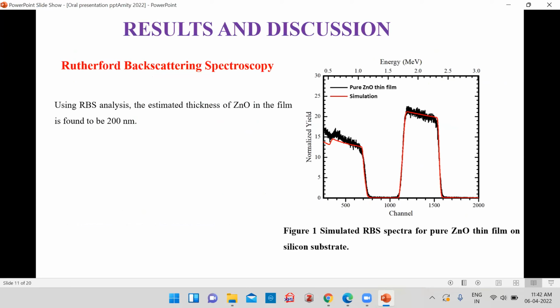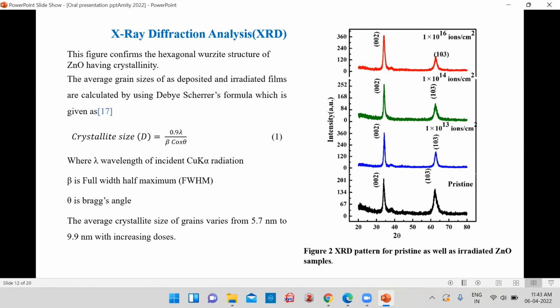This is my XRD pattern of pure ZnO as well as irradiated thin films, which we have done for structural analysis. Two major planes, 002 and 103, are found, and we can see that after irradiation the planes remain stable. This gives stability in the structure, and the 002 plane gives the hexagonal wurtzite structure of ZnO and shows crystallinity. From this we can see that there is an improvement of crystallinity and quality of the film, because there is no shifting in the XRD peaks.